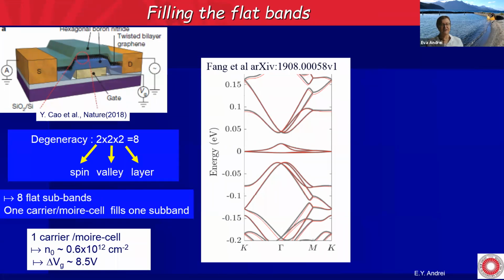Before I go on, let me just go to the nomenclature. What we are interested in is this flat band here, which is close to charge neutrality. It has an 8-fold degeneracy, 2 from spin, 2 from valley, and 2 from layer. So there are 8 degenerate subbands in this flat band. And the way we count the filling of this band, 1 carrier per moire cell corresponds to filling one of these many bands, and it takes about 0.6 times 10 to the 12th electrons per centimeter squared, or in terms of gate voltage, 8.5 volts will fill one of these subbands.